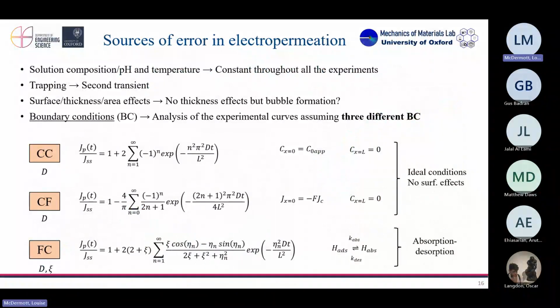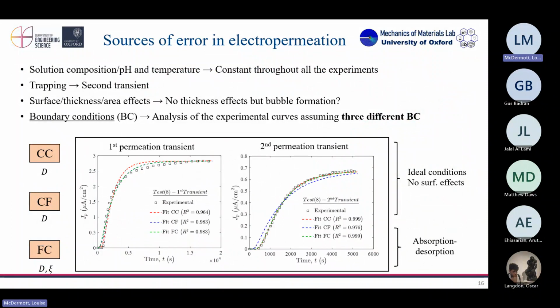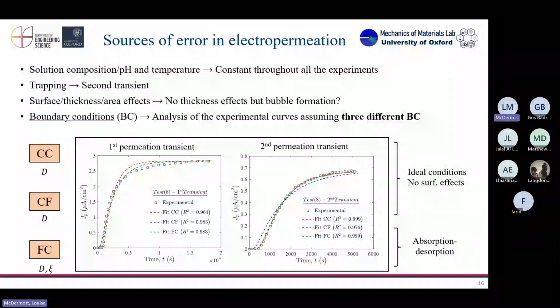So this is one technique, hydrogen permeation, and you can see here the fitting of the curves with different boundary conditions. Even though most of them provide amazing results, with coefficients of higher than 0.96, it's very difficult to really say that with this boundary condition you are getting closer to the results than with this other one.